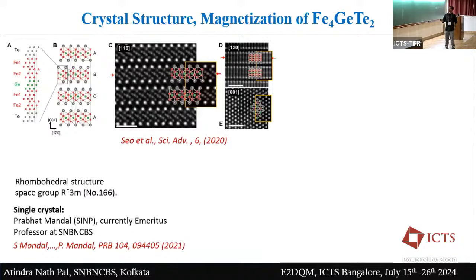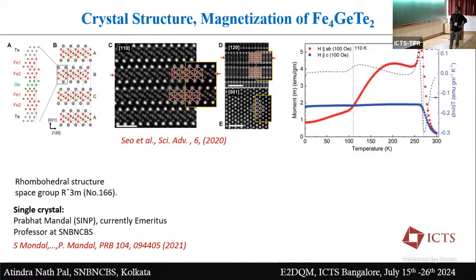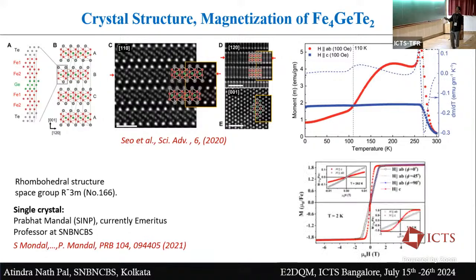So F4GT, you can see a very nice van der Waals structure, and this is a high resolution image where you can see this structure as well, from this paper. Now, if you see the magnetism, you see TC around 270 Kelvin, and this is already an unusual behavior. You can see the magnetization initially increases, there is a spike, and it comes down. This behavior was already studied by Professor Prabhat Mandal's group, and they said that some kind of antiferromagnetic ordering coexists in this case. I'll not discuss this part, but the interesting thing is near 120 Kelvin.